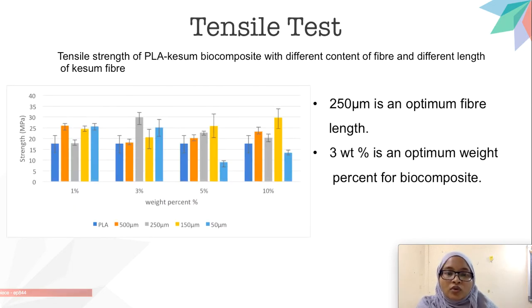Okay, tensile test. The graph below shows the tensile strength of the PLA Kesum biocomposite with different content of fiber and different length of Kesum fiber. As you can see, the grey one shows that 250 micron in size is the optimum fiber length as it recorded the highest strength. And for the content of fiber, 3 weight percent is the optimum weight percent for the biocomposite in order to achieve higher tensile strength.